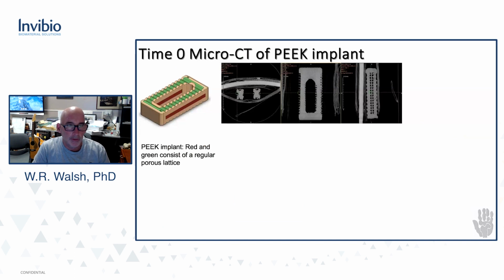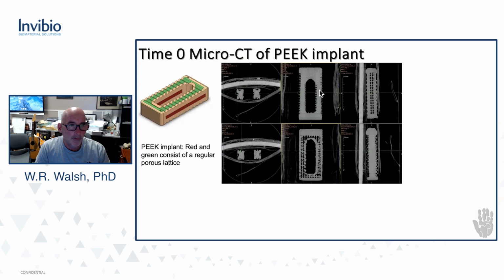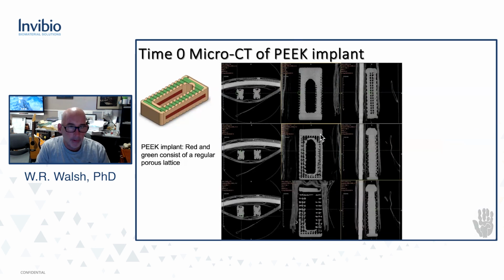So this is just a micro CT of the 3D printed PEEK implant. You can see that we've got porosity and availability at the interface. We've got our aperture, and we can look at it in different planes depending on where we slice it. This is sliced right at the side. This is sliced right in the middle, and you can see the porosity and the available areas for integration.